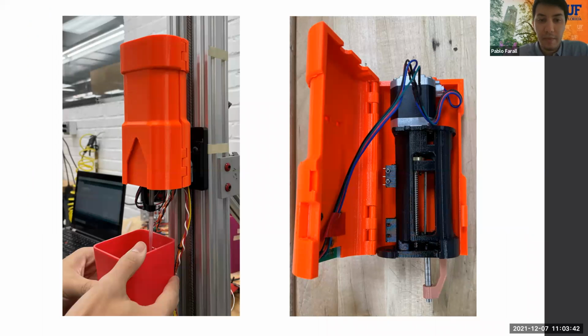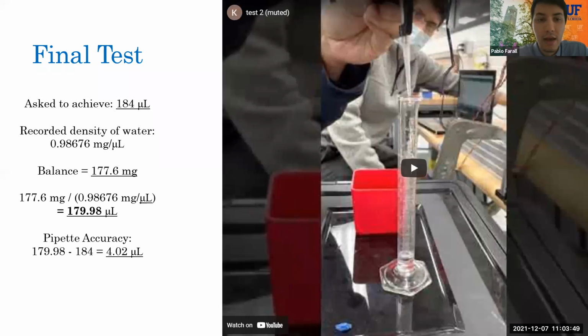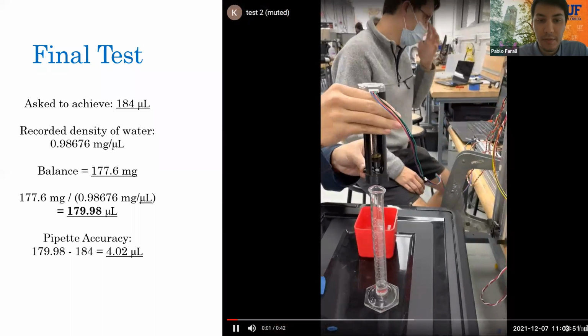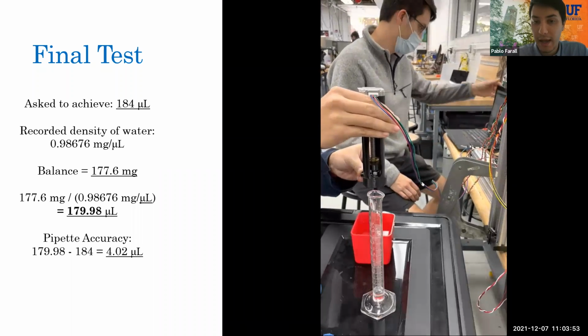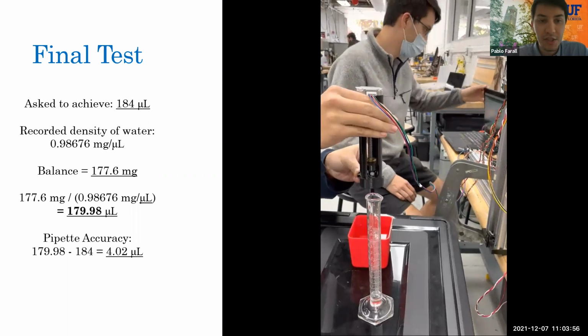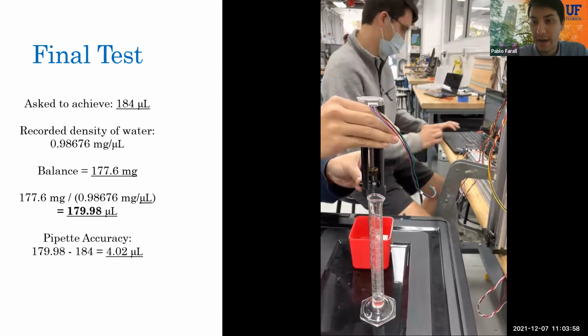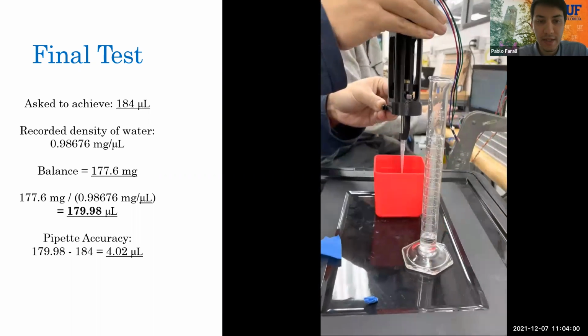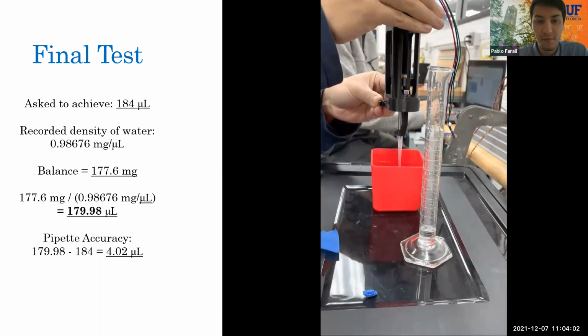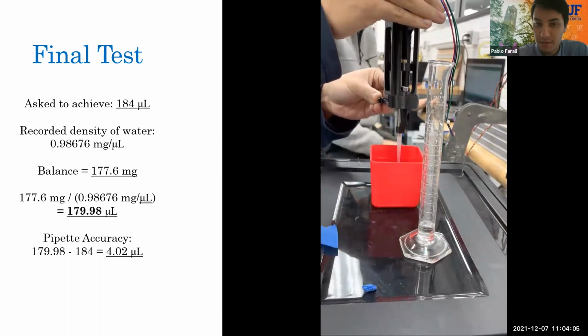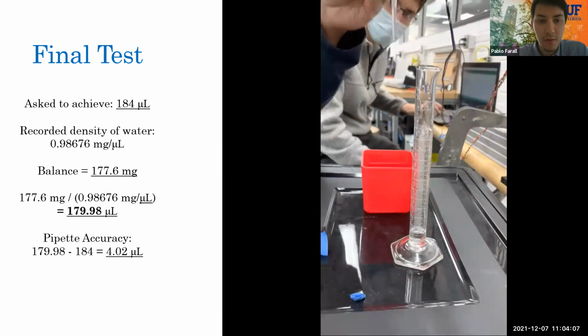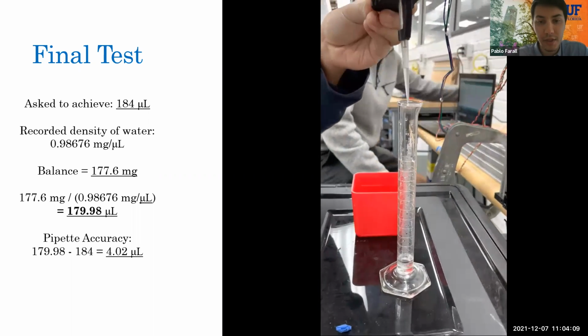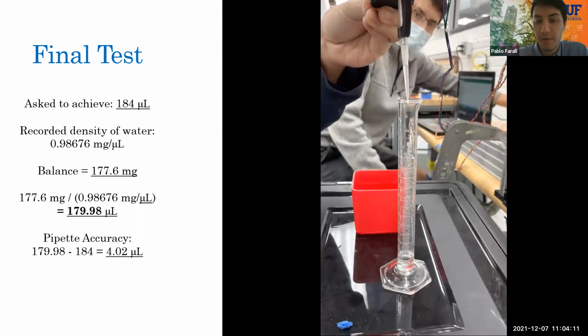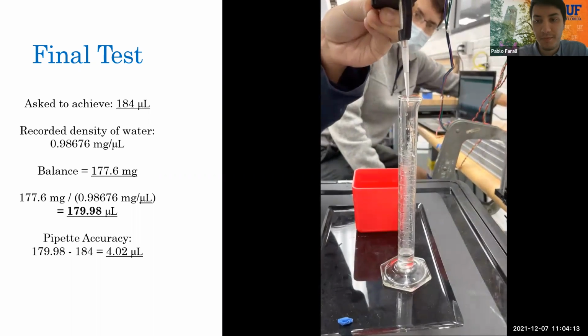Here you can see the pipette in testing mounted to the test stand. And this is the final test that we performed to our pipette after it had been calibrated. We were asked to achieve a volume of 184 microliters. And from the test, we generated a volume of 179.98 microliters. Unfortunately, we were not able to be within 1 microliter, but we were able to be within 5 microliters every time.